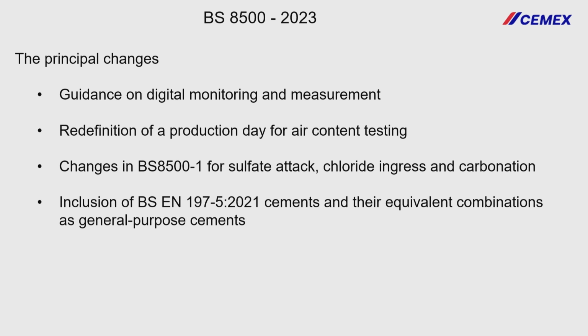So if we're talking about pavement concrete, we used to have to test 1 every 50 cubic meters of concrete. We can now test 1 every 400, in line with compressive strength for conformity. Sulfate attack, chloride ingress and carbonation: again, some changes in BS 8500 Part 1.